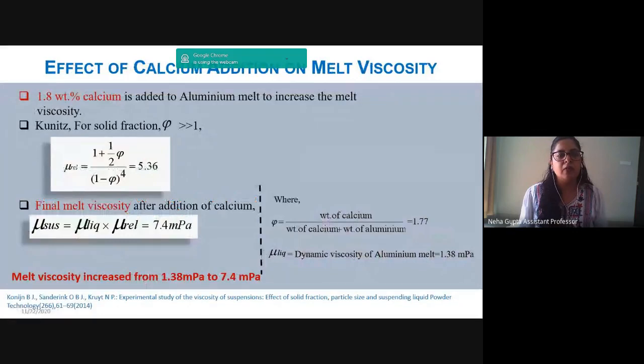So from literature, now they know which different materials they can add as a viscosity enhancer. They have chosen calcium. The physical properties of calcium you already know from literature. Then, using simple calculation, they tried to understand, let us say, if you add 1.8% of calcium to enhance the viscosity, what will be the final viscosity? In that given volume of aluminium, if you add this much calcium, how much viscosity will you achieve? Then you correlate this viscosity with the bubble rise velocity, and check whether you are able to decrease the velocity of the bubble or not. All those calculations they have done.